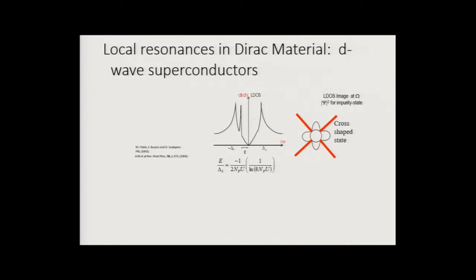And then if you put in a strong enough impurity, you generate the resonance. If you generate many of them, you fill the gap. And if you fill the gap, you kill superconductivity. So that's what's really happening. You probably heard about the Anderson theorem and the suppression of Tc. But if you ask what's actually happening if you don't have a finite concentration of impurities, I put in one or two of these pair-breaking impurities, bad impurities for superconductivity. You don't inflict the damage everywhere, but you do local damage, and you're producing these impurity resonances. They have a net, detrimental effect of filling up the gap. Put differently, if you're coming from the semiconducting world, it's essentially a small gap semiconductor, and defects build an impurity band.